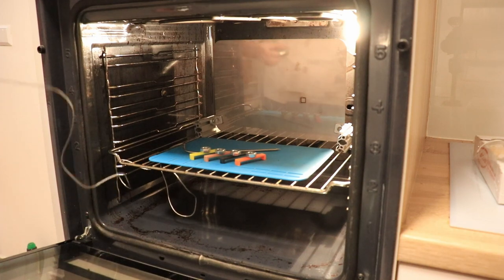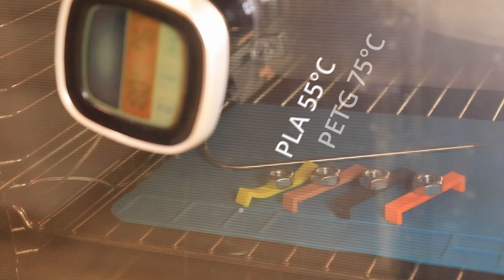Or maybe we will have surprises again. Now, the small modification with this plate means that these results are not completely comparable with those from earlier videos, but they are completely comparable among these four filaments in this test. The first three filaments deformed at the predicted temperature, but the PC blend was a very pleasant surprise. Okay, we stop the experiment now, because it is 175 degrees Celsius.